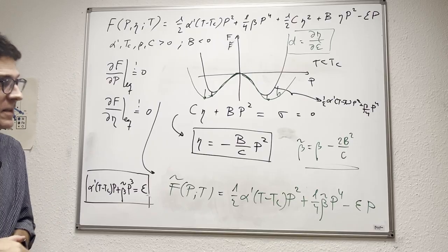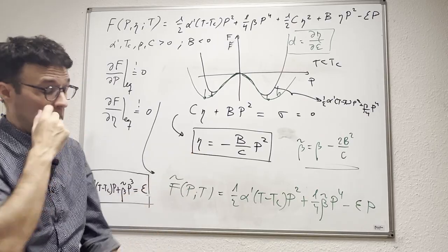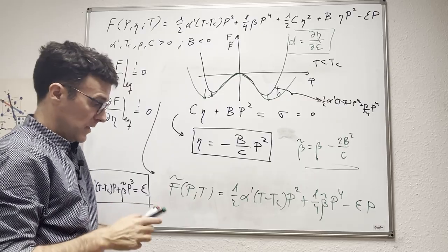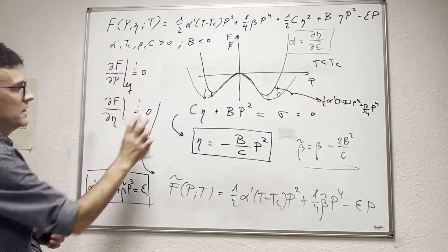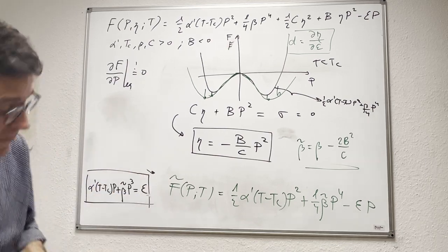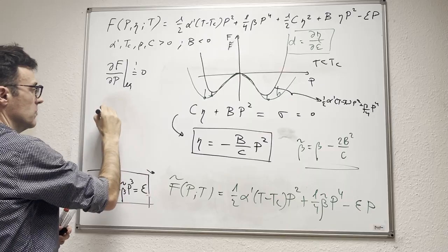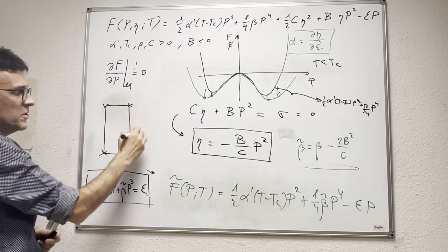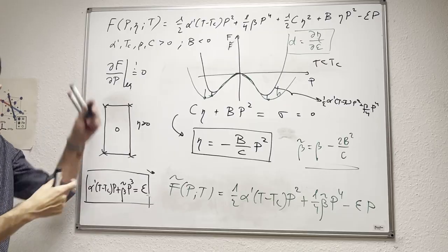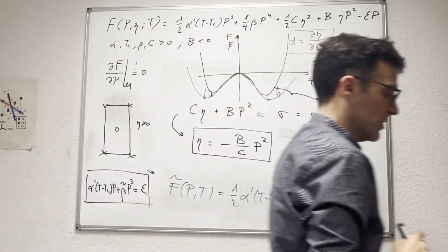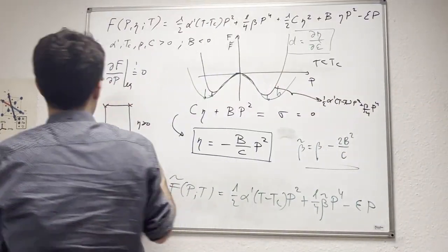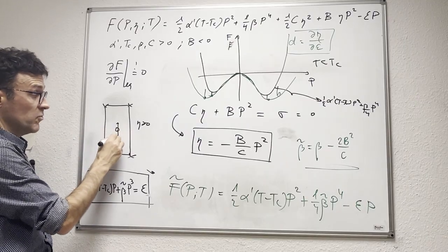What else do we see from these general formulas? Another thing that we see, which is quite nice, and that makes sense with the physics that we discussed the other day, is that the strain doesn't depend on the sign of the polarization. If you remember, the other day we gave a physical argument as to why, when I have a positive strain like this, I strain my little square unit cell that we are always using, I stretch it, I will increase the tendency of the polarization to go out, right? Likewise, in a way that doesn't distinguish between going up or down. Both polar states will be favored by strain.